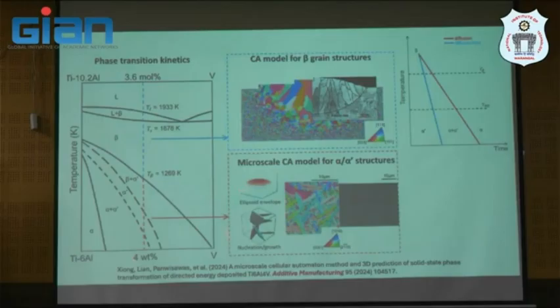structure. So how this actually transforms is important, because in titanium 64, the spacing of the lath is so important for the final property. So we want to see how we can predict it under the condition of 3D printing. And this is where we introduced the framework. The paper was just published very recently, I think less than a month ago. What we do is we first predict the prior beta grain. So what we see is a prior beta grain, and then after that you need to impose the phase transformation from here. Just this point is so complicated.